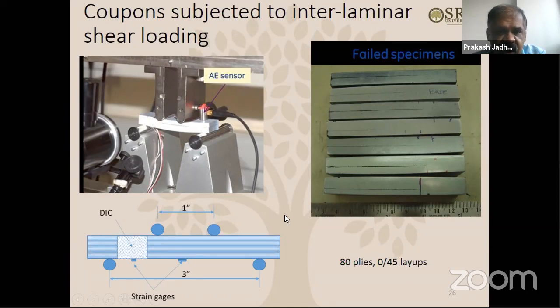So then you will ask me a question: you are also measuring the strain, so why are you not using the strain level at that particular load level? We know what the strain is. But if you look at this strain gauge, it is only telling you the tensile strain here. We don't know what the interlaminar strain is near the ply drop. That's why we have to use so many sensors here, get the data, go back to FEA and validate, and then get back the actual strain levels near the ply drop.